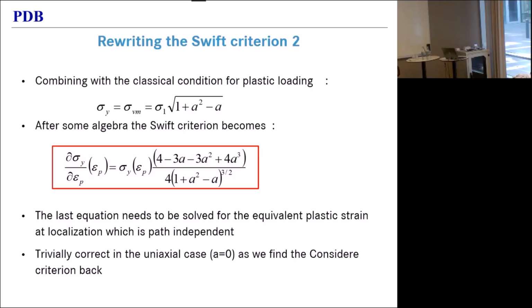And what you end up with is that the tangent modulus, the derivative of the yield stress with respect to the equivalent plastic strain, the tangent to the yield curve, has to become equal to the yield stress multiplied by a function of the state of stress, and to be more precise, by a function of that factor, A. And then we're going to have to solve that equation for every value of A and find for which value of the equivalent plastic strain it is fulfilled.